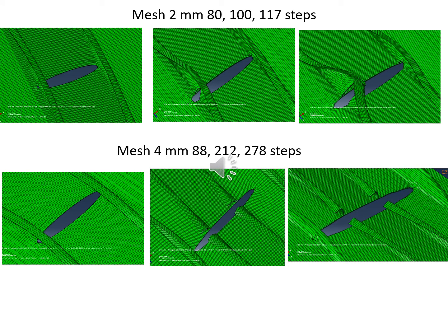Two other different meshes were applied, one based on 2 millimeter elements, the other based on 4 millimeter elements, and some characteristic steps are shown in this slide, indicating that at least in one case of mesh with 2 millimeters, actually stringer do not get cracked all the way. So that is probably the best agreement with the experiments.